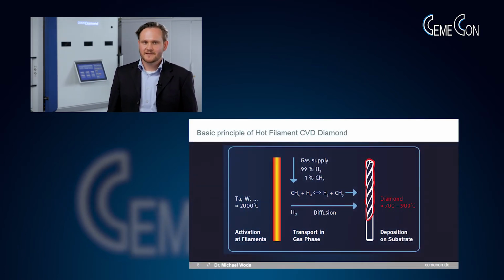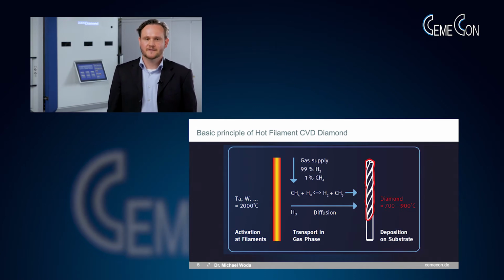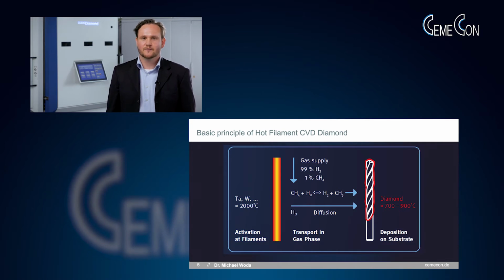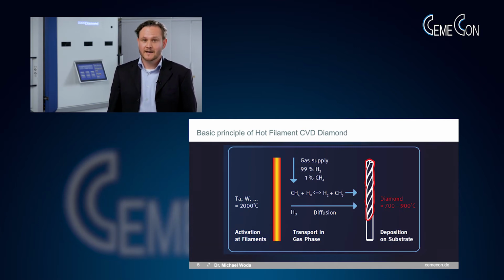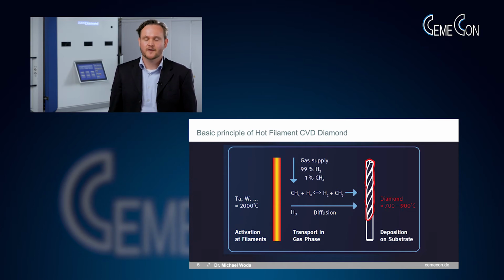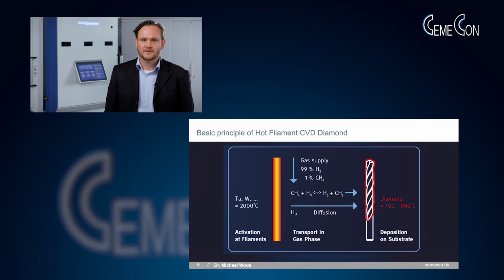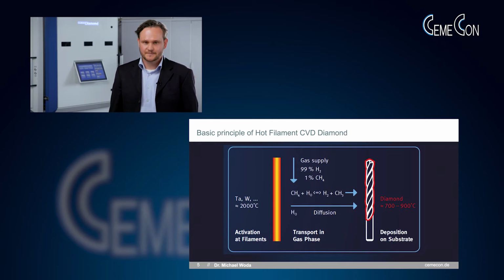On this slide, we pay attention to the basic principle of hot filament CVD diamond coating. We've got three regimes. On the left, we've got the filaments. In the middle, we've got the chemical reaction and transport. On the right, we've got our substrate. Let us start with the left-hand side. The filaments are metallic wires which are heated up by electrical current to about 2000 degrees Celsius. This is enough thermal energy to allow dissociation of the molecular hydrogen into atomic hydrogen.